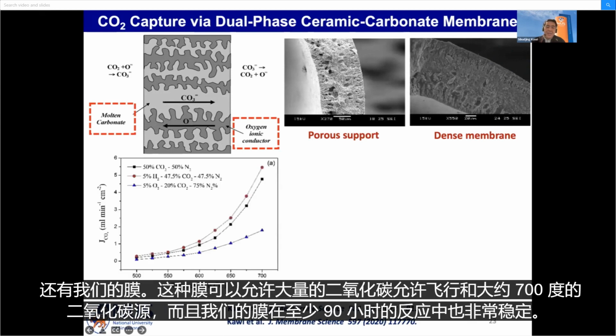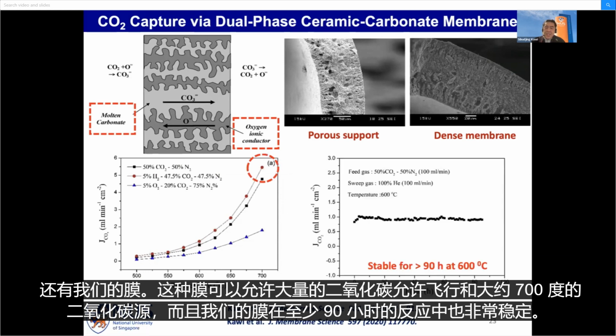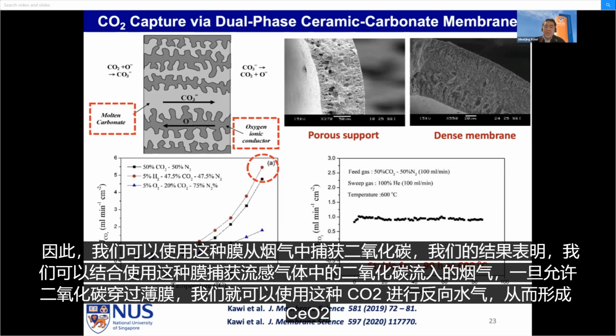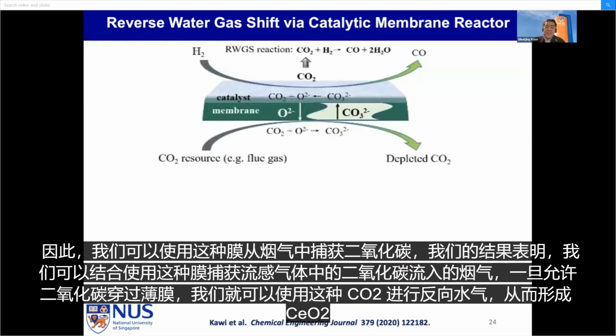And this membrane can permeate a very high amount of CO2, with a high permeation flux at around 700 degrees Celsius. And our membrane is also very stable for more than 90 hours of reactions. So we can use this membrane to capture CO2 from the flue gas. And this is our result showing that the flue gas is coming in, and the CO2 in the flue gas can be captured across this membrane.